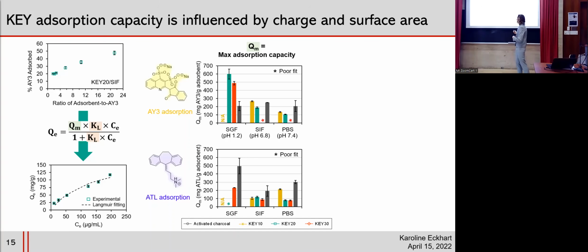And we can see here that the keys adsorb acid yellow 3 as well, if not better, than activated charcoal, the clinical standard. And they actually adsorb much better than activated charcoal in acidic pH, in the simulated gastric fluid. And this makes sense because in acidic pH, we have our anionic drug and the keys are cationic. So not only are we getting electrostatic attraction between the adsorbent and the adsorbate pair, but we're also getting the pi-pi stacking between the hydrophobic block and the hydrophobic drug molecule.